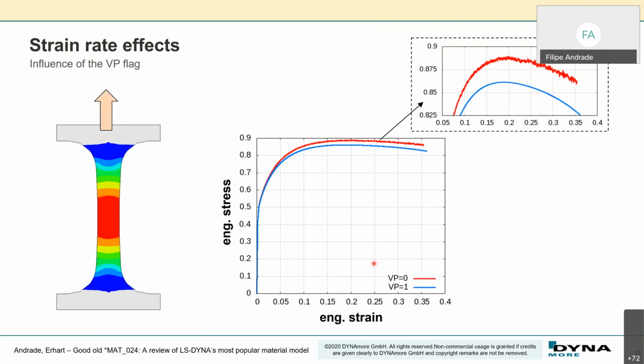And this is again coming from the algorithm. VP0 does not consider that part of that strain rate will be plastic and part will be elastic. It uses everything. So throughout the incremental procedure in the finite element method, you get sometimes a solution which is actually too high for the reality, sometimes it's too low, and then you get those kinds of oscillations. It depends on the material, on the strain rate, on many things, the level of these oscillations. If you have very low strain rates, then the oscillation tends to be not as pronounced as in other cases.